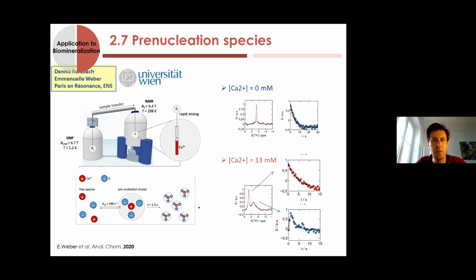In that case, we use DNP methods to reveal the transient species by boosting the magnetization of the phosphate solution first. We prepared two different solutions, a solution of phosphate outside the spectrometer, and a solution of calcium inside the spectrometer. We do the DNP experiment on the phosphate, then transfer the phosphate solution into the tube, and start recording the spectra as soon as we mix the two solutions.